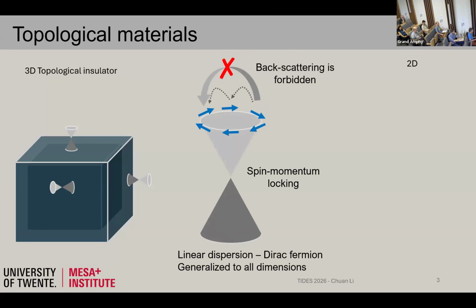However, the tricky thing here is that with 2D surfaces, direct backscattering is fully forbidden by the Dirac structure. However, processes with intermediate steps are allowed. So if you have such intermediate states, the total backscattering rate will not be zero. It's finite.